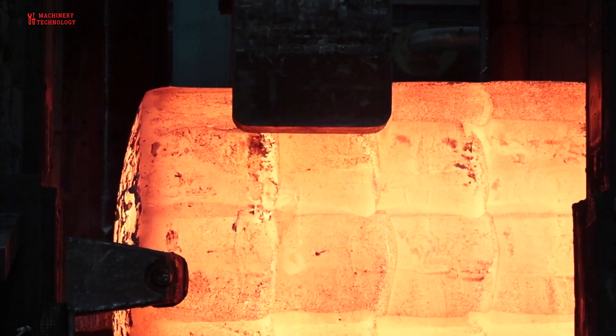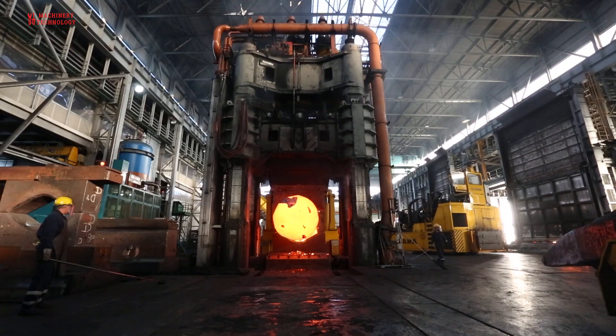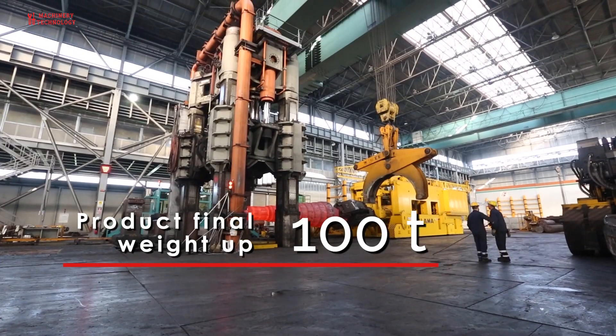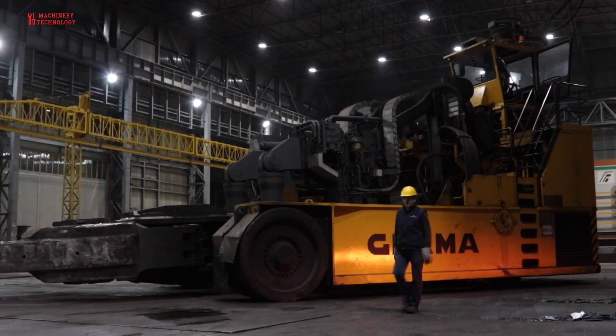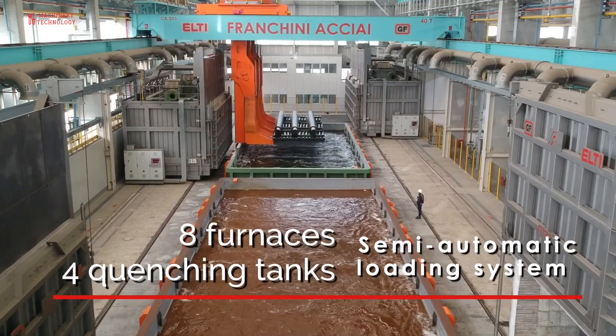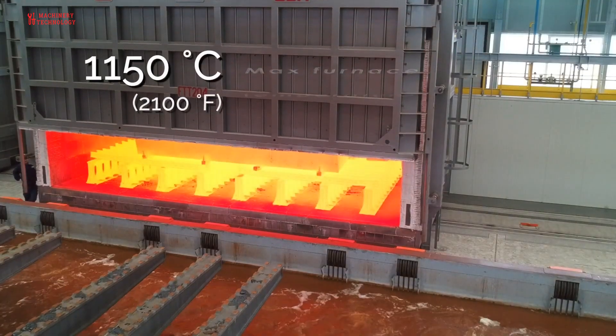A state-of-the-art department dedicated to heat treatment gives forged parts the required mechanical and metallurgical characteristics. The furnaces, which can move on rails, reach temperatures up to 1,150°C and are equipped with advanced control systems. The tanks are equipped with propellers with adjustable spray to obtain adequate quenching, with a quenching medium that can be selected between water and a polymer. The length of heat-treated parts can reach up to 24 meters. The automatic loading system allows treating multiple pieces simultaneously and controlling the relevant transfer times.